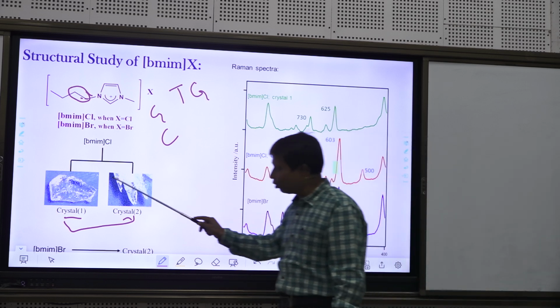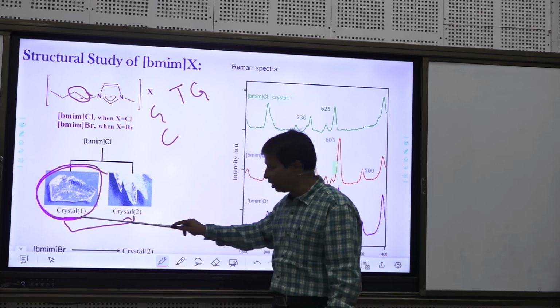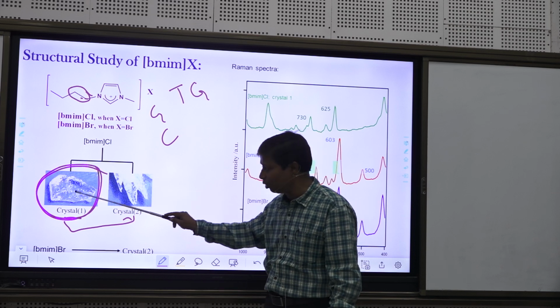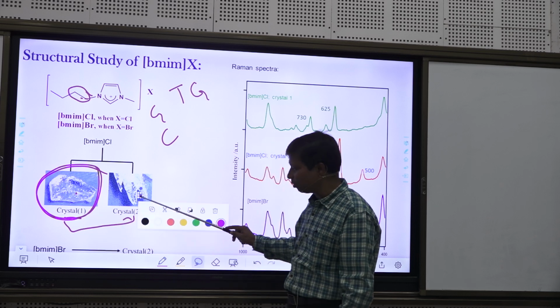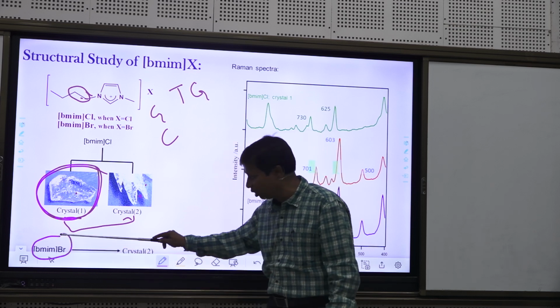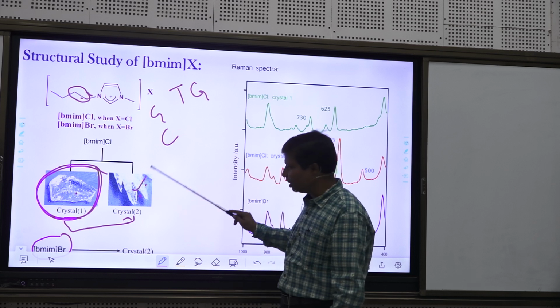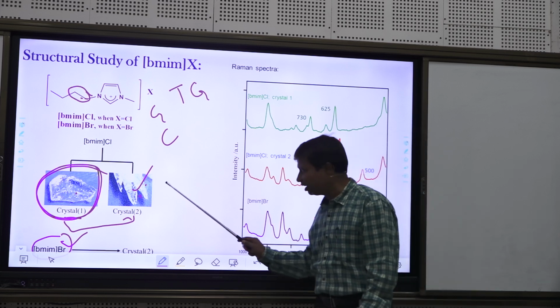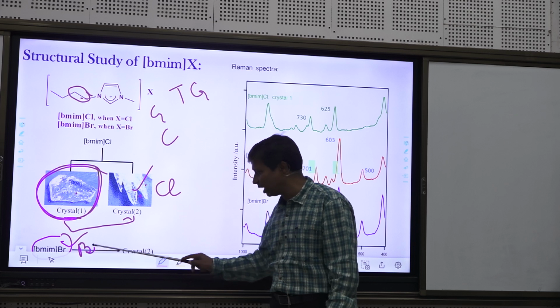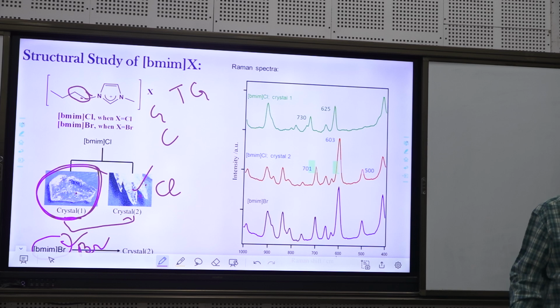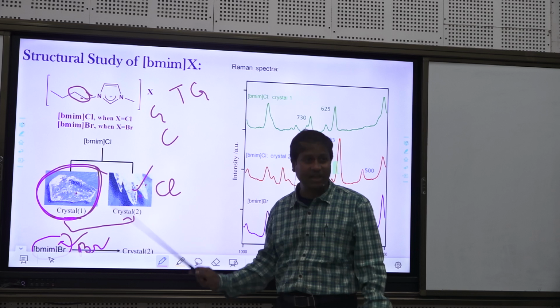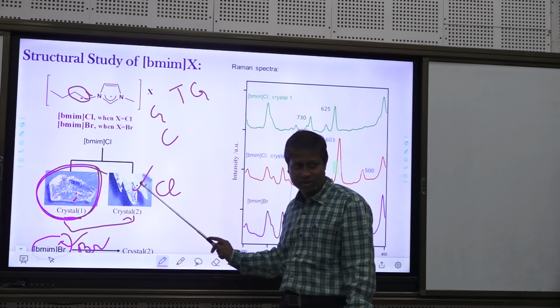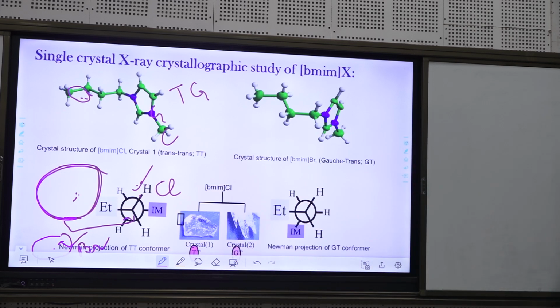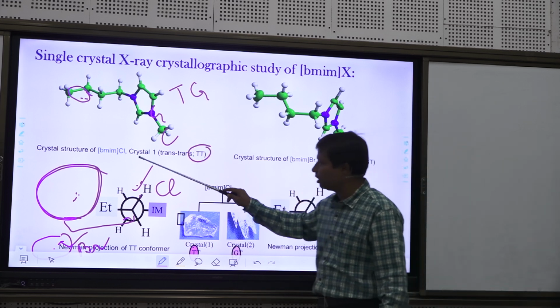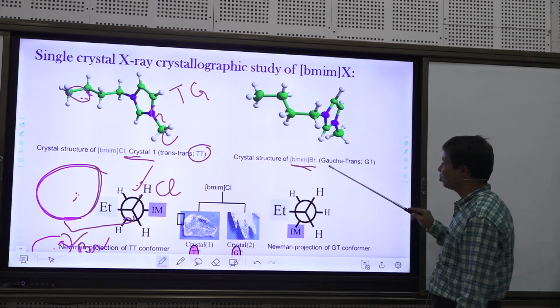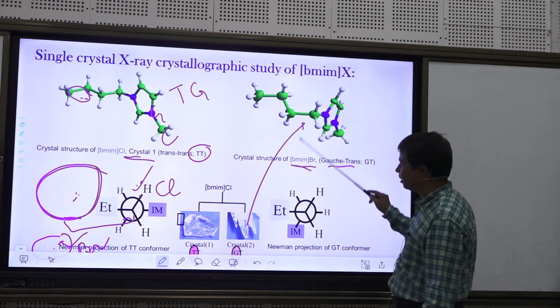And we were lucky to have low temperature X-ray crystallographic data. That's why we know the crystal structure, the molecular structure of this one. We did not get any crystal structure of this molecule, but we got a crystal structure of this molecule, and then we saw that the Raman spectrum of this molecule and this molecule is very identical. The difference is that this molecule has chloride as an anion and this molecule has bromide as an anion, and neither anion is Raman active because it's just an atom. So definitely the cation structure should be the same. This one we found is trans, and this one we found is gauche trans. So with the help of X-ray crystallography, we got this one as trans for crystal 1, and this one is the BMIM bromide. So this is gauche trans, and then we concluded that this structure is this and this structure is this.